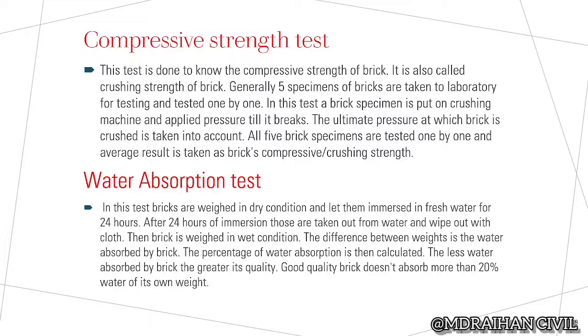Then the bricks are weighed in wet condition. From the difference between wet and dry weight, the percentage of water absorption is calculated. The less water absorbed by the brick, the greater its quality. Good quality bricks don't absorb more than 20% water of their own weight.